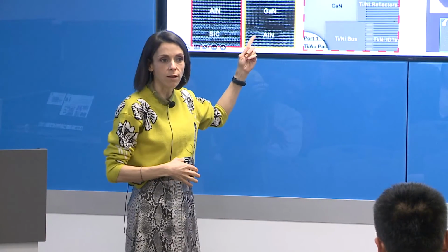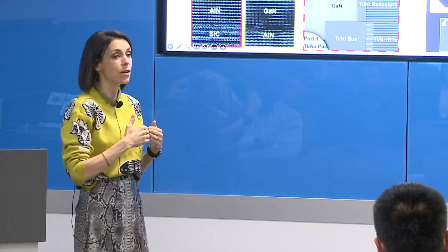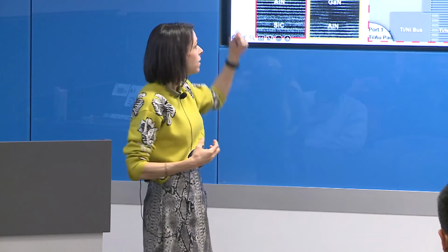That thinning down, the high quality of the gallium nitride, and the high thermal conductivity all translate to allowing us to scale gallium nitride, which is a piezoelectric semiconductor, up to 15 gigahertz frequencies and above, and to do so with very low propagation loss because it's so pristine, and to be able to support 60 dBm of power handling, because the heat that's generated, whether it's from the RF signal or from the vibrations themselves, sinks through the silicon carbide, which is a beautiful thermal conductor, very nicely. And we can think about filters for wireless communication in that space. So that's just a start.